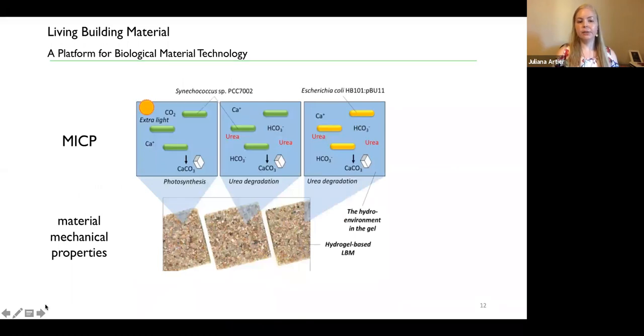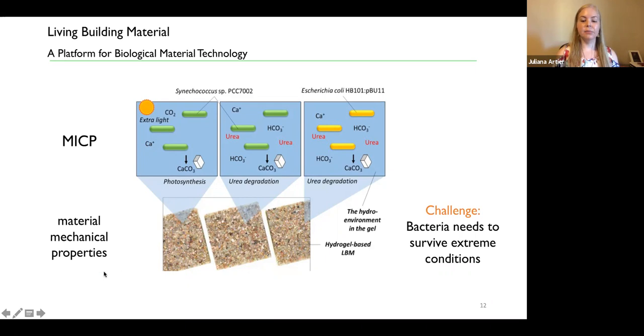So in our work here in our platform, we were focusing on two different organisms: our model organism, which is a photosynthetic cyanobacteria, and also the Escherichia coli that has been previously engineered, receiving the operon for the urea degradation enzymes. And we use this technology of MICP to increase the material mechanical properties of our bricks. And one of the problems is that because these bricks are going to be used later for constructions, they need to dry, and we need to keep the bacteria alive under these extreme conditions.